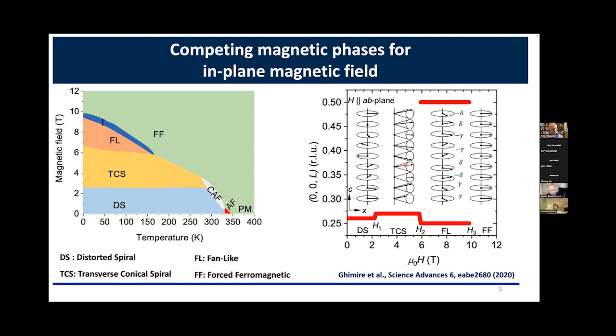And then you further increase the magnetic field. These spins now find it easier to flop back into the plane. When they flop back into the plane, this is a planar state, and it's not a spiral state. It has a 2q vector, as you can see here in this cartoon picture that I drew. I noted here that this is one q vector and this is another q vector, and we understand very nicely why this happens. I'm not going into the details of this, and then it goes into the forced ferromagnetic state. So there are a lot of competing magnetic phases that can be tuned with external magnetic field.